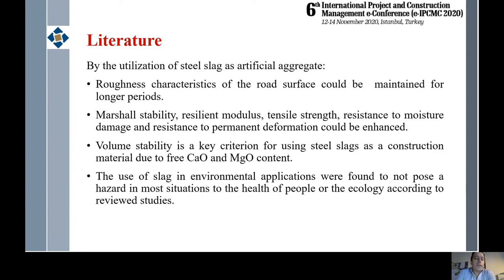One of them was volume instability. As I noted here, volume stability is a key criterion for using steel slag as a construction material due to free calcium oxide and magnesium oxide content. And the second disadvantage of steel slag is its high heavy metal concentration. The use of steel slag in environmental applications was found not to pose a hazard in most situations to the health of people or the ecology, according to reviewed studies.